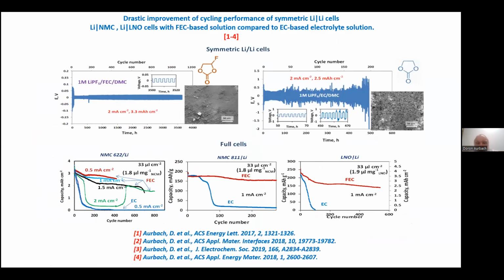So what I show you here are results from symmetric lithium cells. So we take a lithium cell and we use an electrolyte solution that contains FEC as a fluorinated co-solvent, and we have unique surface reactions on the lithium. We form exactly our ideal surface films. And now we can cycle thousands of cycles, and we measure the voltage profiles of the symmetric cells to see how stable they are. This is an experiment that took thousands of hours, and this is a continuum of voltage profiles that we measure.